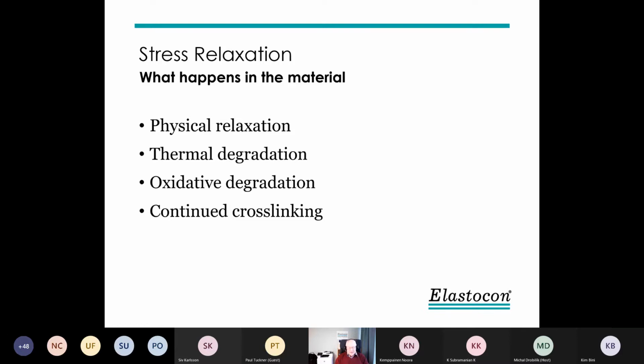But in rubber, we have another thing. We can also have some continued cross-linking. If we have not cured the material properly before we do the test, we will also get some extra crosslinks in the compressed state. And that is affecting the result, of course, but not so much as it will affect the result if we make compression set, because there you see it much more. But it's always, say, a good idea to have a good cured material when you do a test. Otherwise, it will not be what you expect it to be.